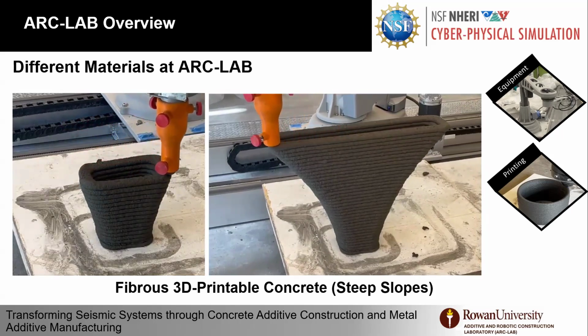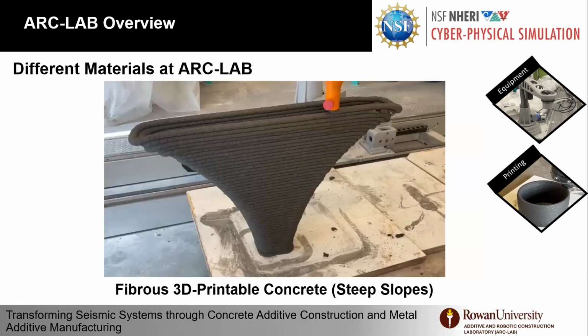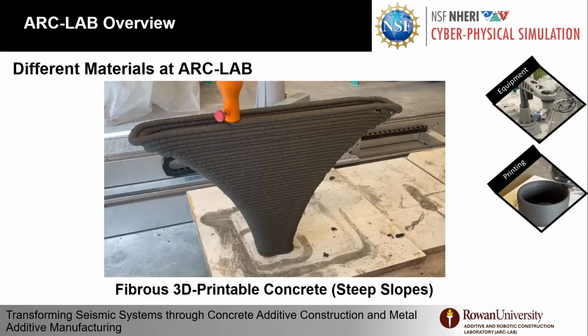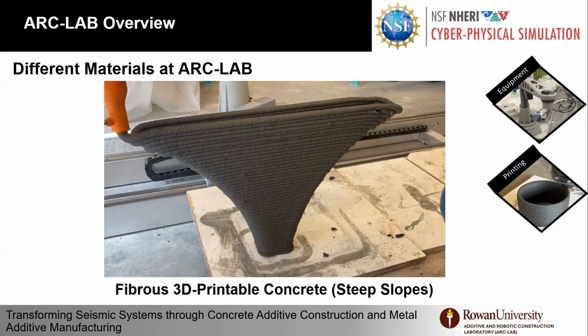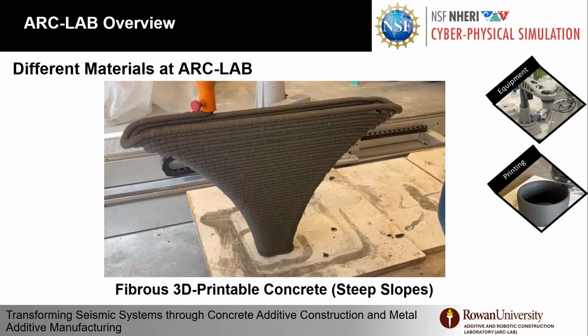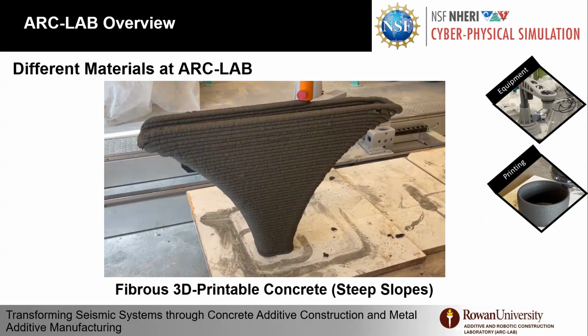We actually test also what's called stress testing. So we print until we fail to understand the material behavior. As you can see here, we keep printing on a slope, and this one, if you take a tangent at the end, is almost a 65-degree slope, but with a lot of deformation on this overhang. As you can see here, the material is almost hanging in the air, and now there's a fight between the material trying to collapse and trying to hold itself, and that's actually the slope that you can say is a safe slope to print.